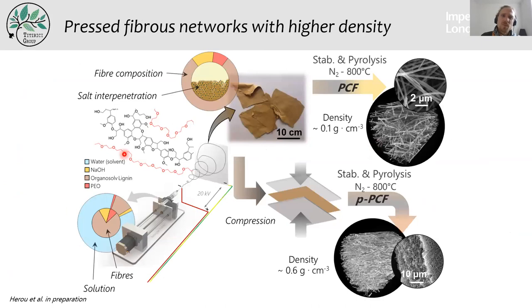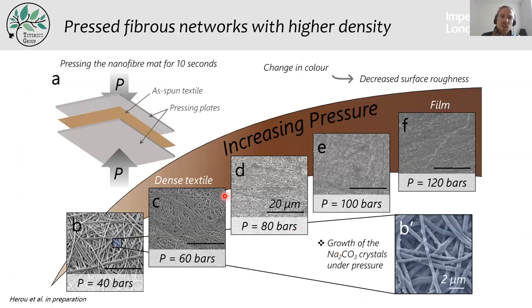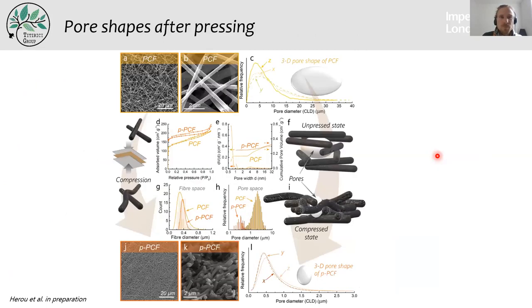So we did the same system where we compared basically the previous sample that was pyrolyzed just after electrospinning, and a sample where we compress these mats with different number of layers and we carbonize later. And we can see that the density increases by a factor 6 approximately. If we look on the SEM, this compressed sample before carbonization, you can see the more we increase the pressure, the more the fibers start merging into the film, which increases the density.